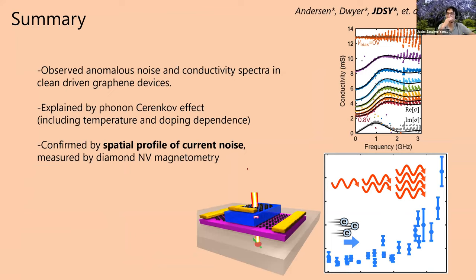Yeah, that's a great question. We wondered exactly about that. Basically, we did an analysis where probably they are actually reflecting, after some percentage of them reflects off the edge of the sample. But then once they reflect, they're moving in the wrong direction. You can analyze what happens to those phonons that get reflected, and they will very quickly decay because they're in the wrong direction for the amplification process. So it's in the model. It comes out very cleanly that those would just be extinguished. Okay, thank you. Not a problem.